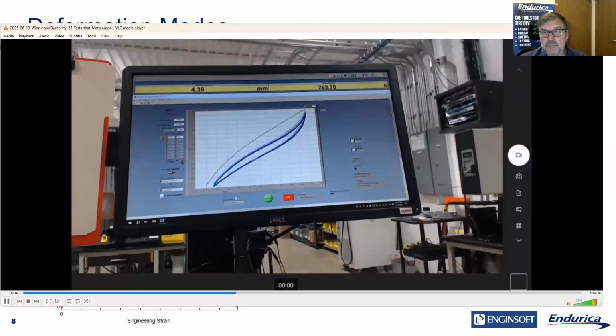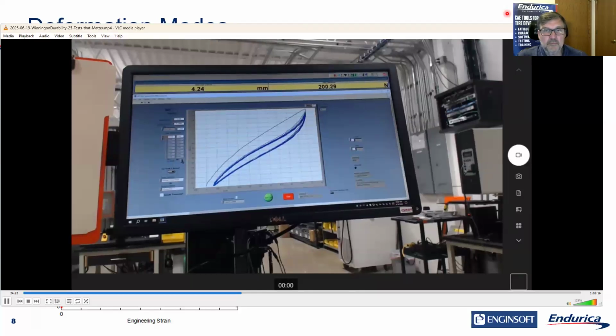Okay. All right. We saw tension. We saw biaxial. We saw that this is planar tension, which some people often call pure shear. The really important thing is that we're assuming it doesn't move in on the sides, because it's basically infinitely wide compared to its height. There's a closed form solution, and the tension test, the biaxial test, and the planar test all have closed form solutions, and we can numerically fit them with an optimizer, and they all fit nicely on the blue surface that Tom showed a couple slides ago.